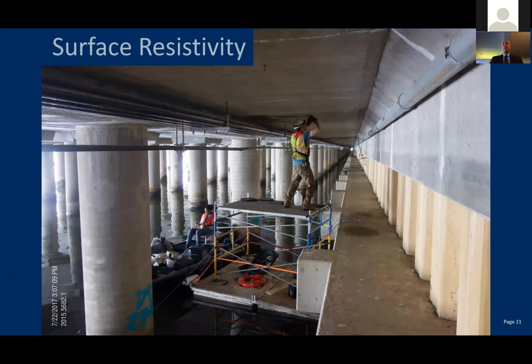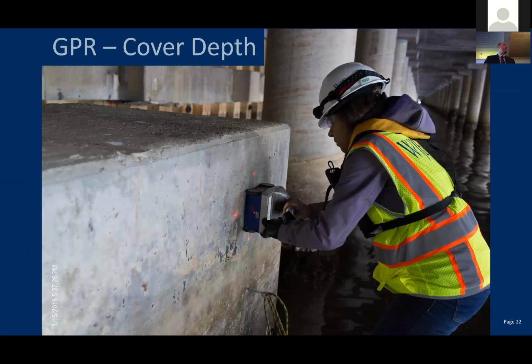And another technique is surface resistivity. And it's an indication of permeability of chloride ions. So it kind of gives you an indication of how good the concrete construction was originally. In addition to those techniques, we also use GPR to do our cover depth measurements. There's quite a bit that is needed for the service life modeling. And so these are just incorporation of the actual cover.